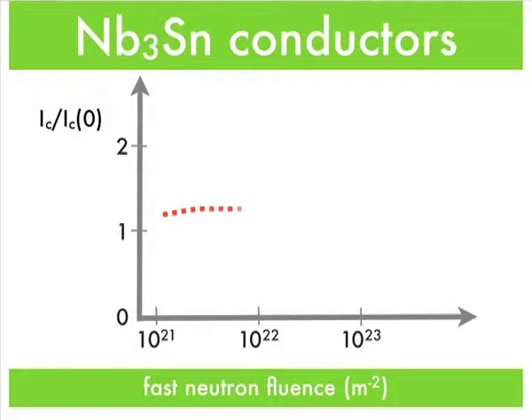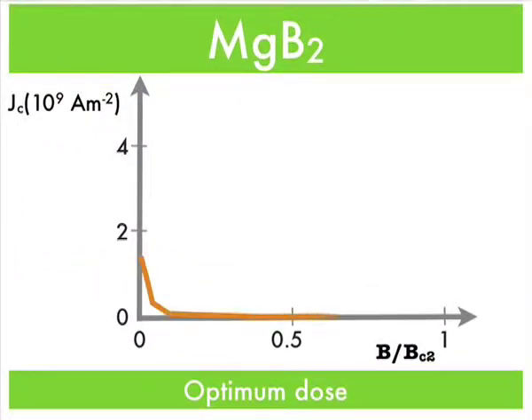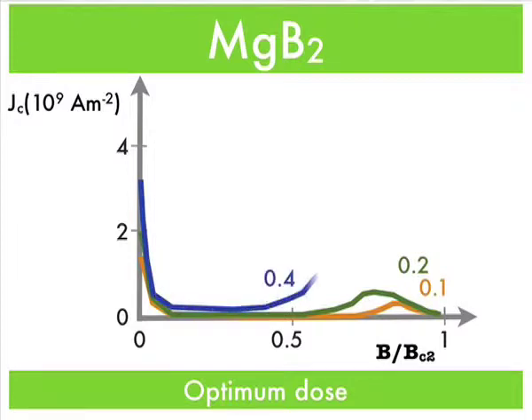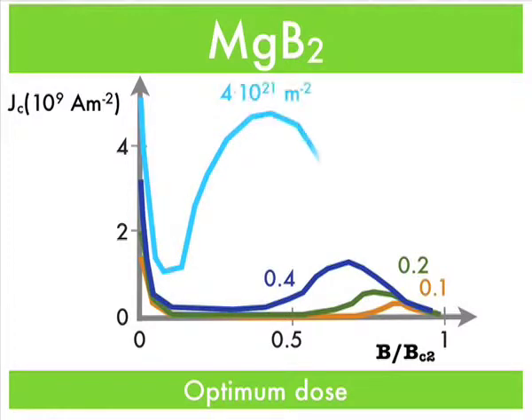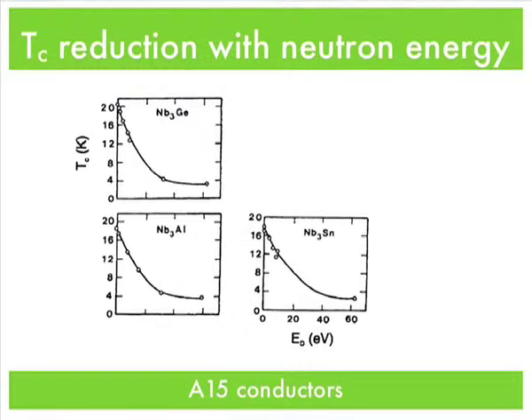The general observation is that you get an increase in critical current densities initially — at low doses you reach a maximum — and then when the basic superconducting properties degrade too much, the critical current densities will go down. The transition temperature starts to decrease, and that can be very dramatic. You can even drive a material into the normal conducting state if you go to very high doses.